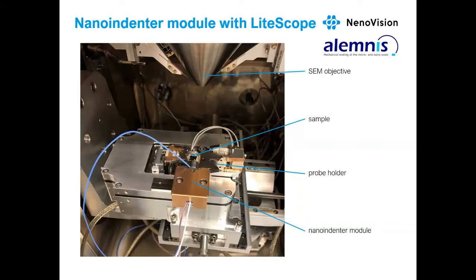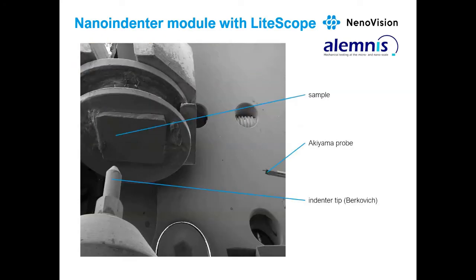Here is an image of how it actually looks in the SEM chamber. We have the Nanoindenter module over here, the sample, and the probe holder for the AFM tip. As we change to the SEM image in wide field, we can see both of the tips. We have the Akiyama probe or another AFM probe and the Nanoindentation tip, here Berkovich. With the fixed distance between the tip of the AFM and the Nanoindenter, we can move with exact precision to the contact with both tips.